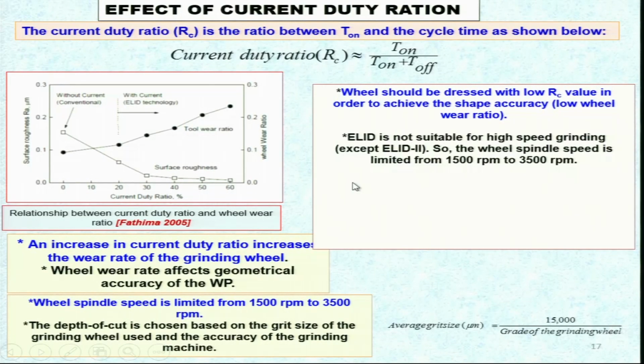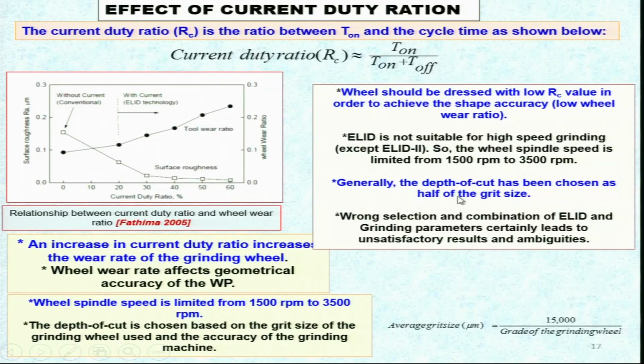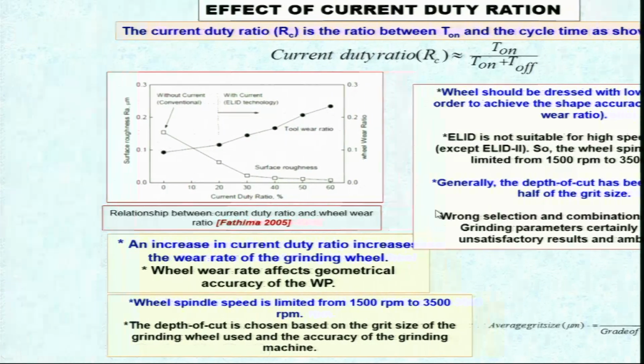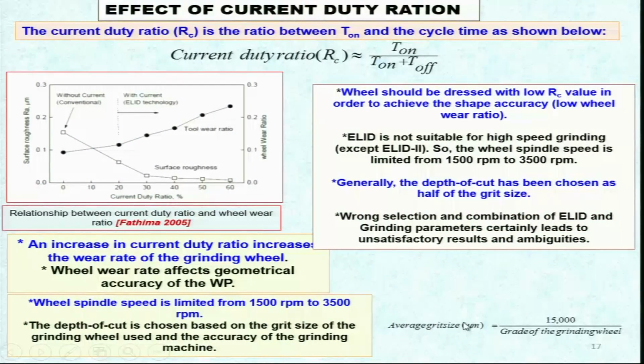ELID is not suitable for high speed grinding except in the case of ELID 2, which we have already seen. So, the wheel spindle speed is limited to 1500 to 3500 RPM. Generally, the depth of cut is chosen as half the grit size, because as I have mentioned already, it depends upon the protrusion of the grits on the grinding wheel also. Wrong selection and combination of ELID and grinding parameters certainly leads to unsatisfactory results and ambiguities on the finished component. As you can see here, average grit size can be calculated by this formula.